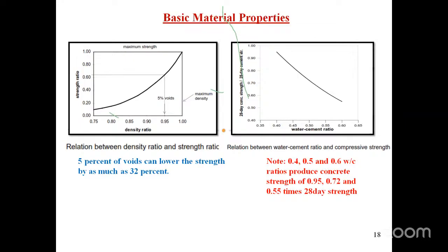Listen carefully, water cement ratio 0.4, 0.5, 0.6. Suppose you use 0.6, what percentage of strength do you get? Only 55% strength. How much strength reduced? 45% strength is getting reduced when you increase water cement ratio from 0.4 to 0.6.